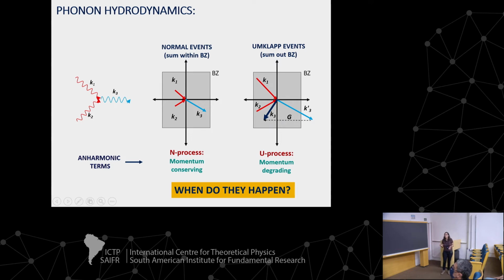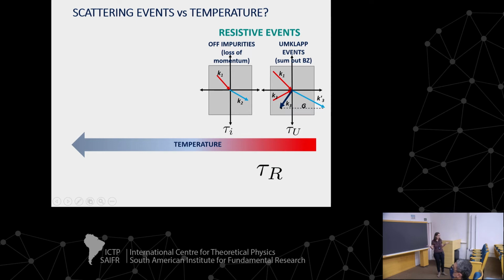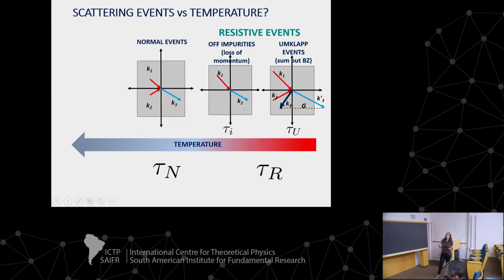We can ask, when can we expect to see them? So I will make a representation against the temperature. This is very qualitative, because I have to point out something about that. But in a very general way, resistive events are the ones we can expect to see rather at higher temperature. Phonon branches are populated, and so we have phonons that are more energetic, so it's more likely that they interact with a momentum that goes out of the Brillouin zone. Impurities are there over the whole temperature, but it's more likely the interaction when we have more phonons available for that. Anyway, the impurities don't disappear with temperature. So when we go to lower temperature, phonons become less energetic, so we can expect to see this happen.